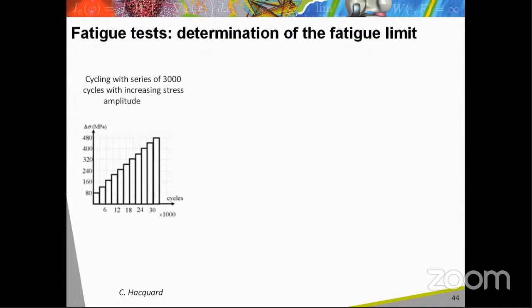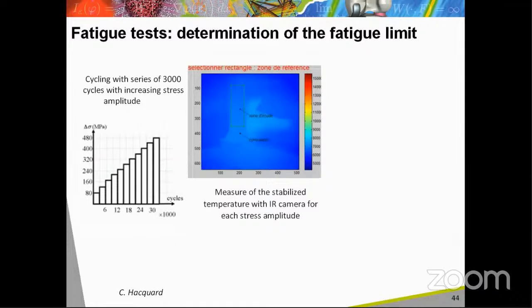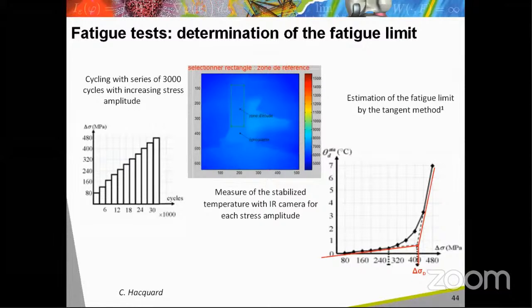Series of 3000 cycles at a given stress amplitude are applied on the samples, with increasing the stress amplitude at each new series, as described on the left figure of this slide. The heat dissipated by the sample is measured using an infrared camera. The stabilized temperature versus the stress amplitude is given in the right figure. The stabilized temperature increases linearly, and then an increase is observed above a stress level that corresponds to the fatigue limit, as confirmed by some recent studies.